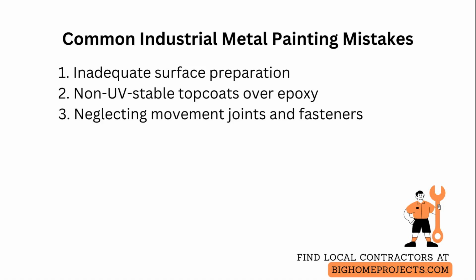A third issue is neglecting movement joints and fastener areas, which causes cracking or underfilm corrosion. Resolve this by applying flexible caulk to joints, assuring proper edge sealing, and using compatible primers around fasteners.